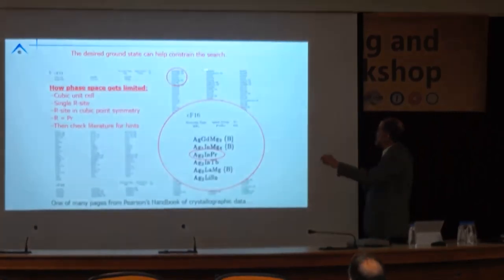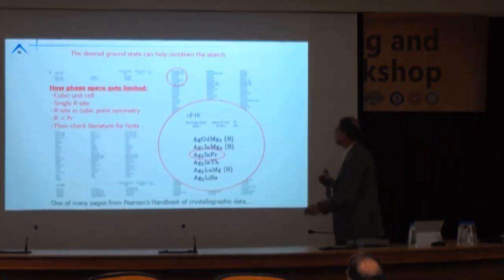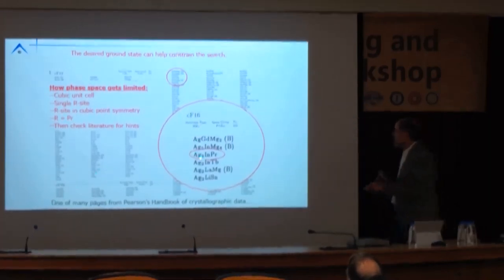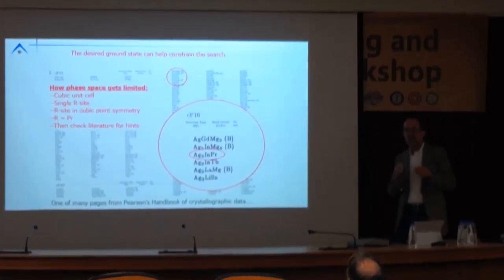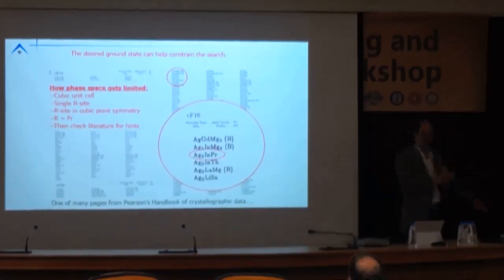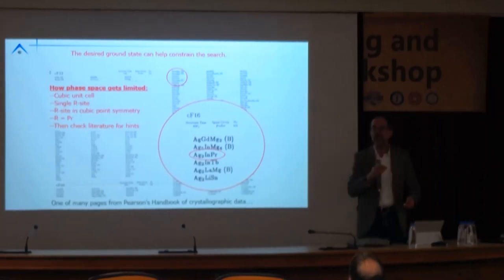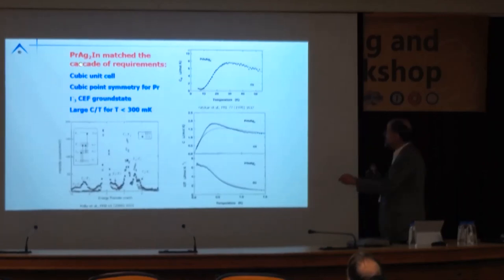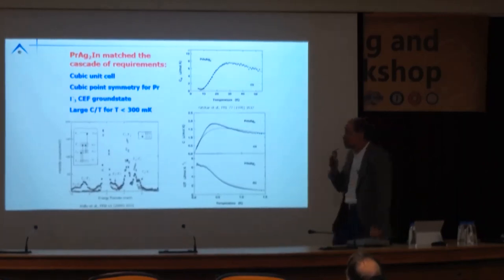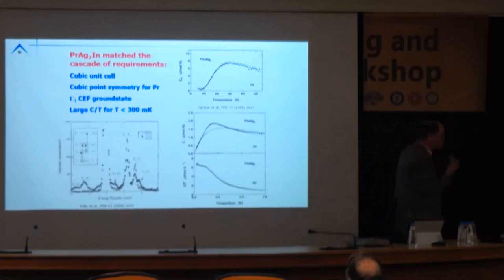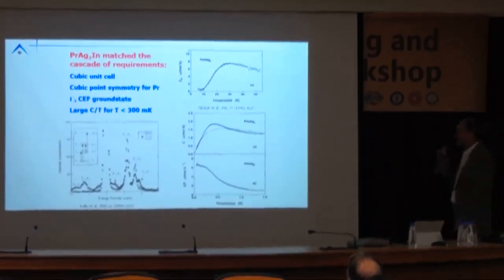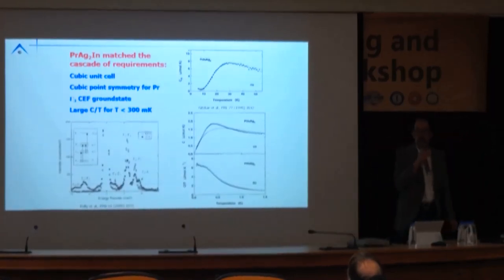Okay? So here's one of these pages off of old Pearson's. Here's the CF16, BiF3, also known as the Heusler structure. Here's silver 2 indium praseodymium. That fit all these criteria. So did PrPb3, so did a few other materials. You can then see what literature has to say about it, okay? It turns out that Pr Ag2 In had been looked at by Rossat-Mignod and co-workers in Grenoble in the 70s and 80s in a desire and attempt to find singlet praseodymium compounds. This was a failure. They wrote it up in a proceedings and moved on.